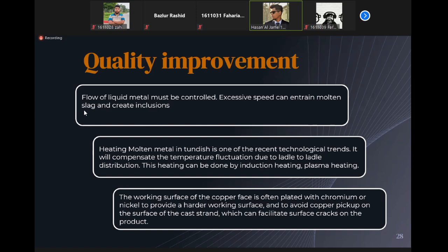Then heating the molten metal in the tundish is one of the recent technologies that are used. Heating can be done by induction heating or plasma heating. It will compensate the temperature fluctuation due to ladle to ladle distribution. The working surface of the copper mold is often plated with chromium or nickel to provide a harder working surface and to avoid copper being picked up on the surface of the cast strand, which can facilitate surface cracks on the product. That's why sometimes we also use the mold flux, as I mentioned before.